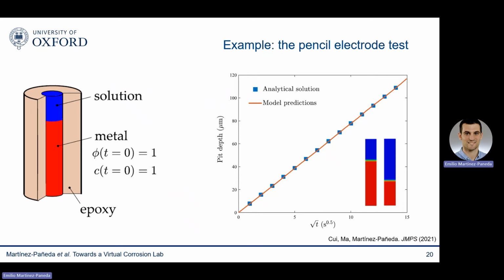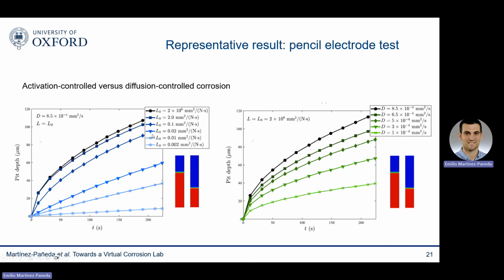But also important, we want to show that the model can capture naturally the transition from activation control corrosion to diffusion control corrosion. You can see here on the left that if we ramp up the corrosion current density through this L parameter, the mobility coefficient, we go from the linear behavior of activation control corrosion to the parabolic behavior of diffusion control corrosion. And of course, when we are in the diffusion control corrosion regime, then the pit depth is going to be very sensitive to our choice of diffusion coefficient. So there's another key takeaway. You don't have to worry about going from activation to diffusion control corrosion, adding some sort of criteria that you need to change in time and space, because the model can naturally capture this.